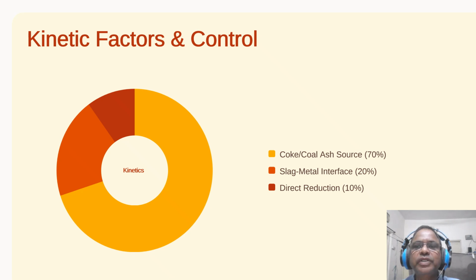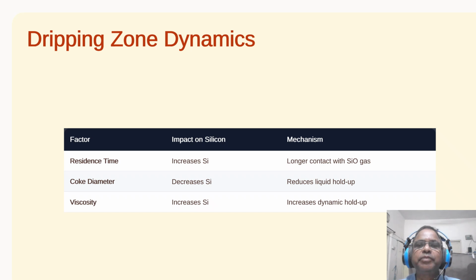Now, let's zoom into the most chaotic part of the furnace, the dripping zone. Coming to our next slide, which elaborates on the dripping zone dynamics. So imagine a giant high-speed obstacle course. That's the dripping zone. This table shows us how the physics of the furnace affect silicon. If iron takes longer to fall, what we call residence time, it has more time to breathe in that SiO gas, and silicon goes up. If you use bigger coke, the iron drips through faster and silicon goes down. Even the thickness or the viscosity of the iron matters. Basically, anything that slows down the iron's journey to the bottom is going to increase your silicon content. But here is the weird part. Sometimes the silicon actually goes down once it hits the bottom.